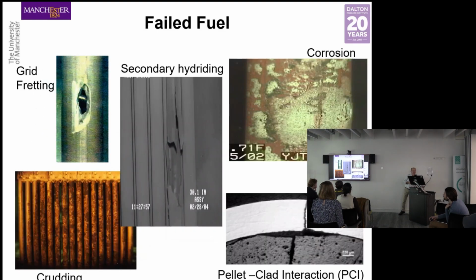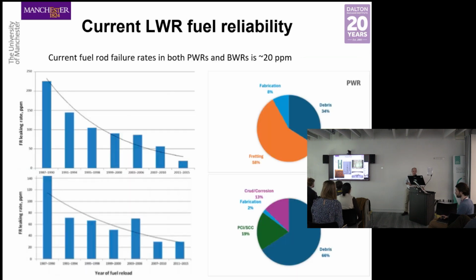We won't go into all the phenomena, but here are some pictures of fuel failure mechanisms. We talked about pellet cladding interaction and these cracks being exacerbated by the presence of a stress corrodant, normally iodine in our case. The fuel can corrode from the outside. Once it's corroded, then hydrogen that's liberated from the corrosion reaction can be taken up by the cladding, and that gives rise to secondary failures called secondary hydriding. Crudding is a whole separate discussion in itself. And every so often, we get rubbing that takes place between the grids and the fuel rods, and we get these so-called fretting scars, where simple rubbing between the fuel rod and the grid gives rise to a hole in the fuel rod. So the fuel fails in some fairly interesting ways.